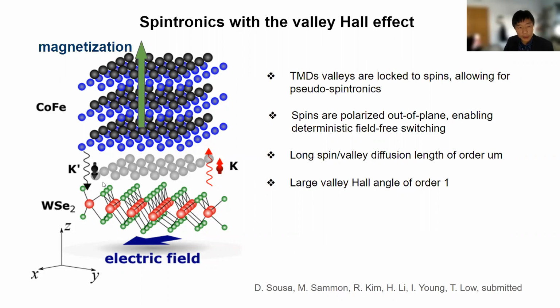What is interesting about this material is that for the valence band, the K valley and the K prime valley have different spin polarization. In one valley, the spin is pointing up, and in the other valley, the spin is pointing down. And the nice thing about this spin texture is that all the spins are pointing in the Z direction, which is basically what we are looking for in order to switch a perpendicular magnetization. So we decided to look at this material and study the efficiency of spin injection into the cobalt iron or other types of magnetic materials, and also to compute what is the figure of merit for these materials.